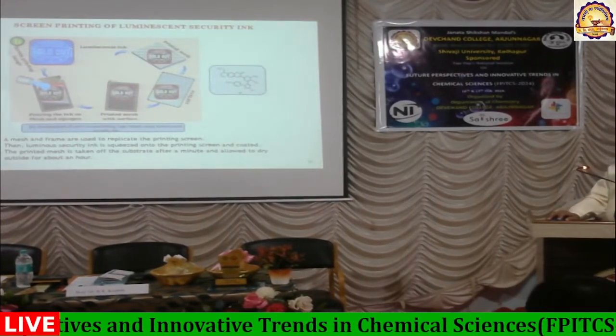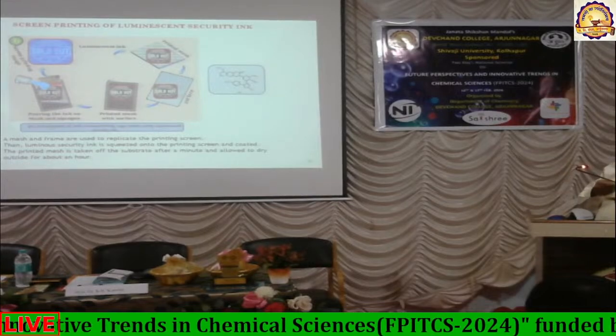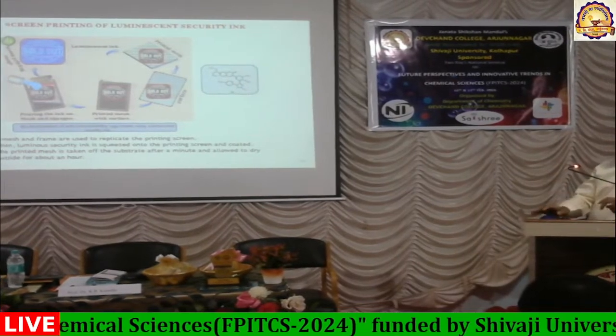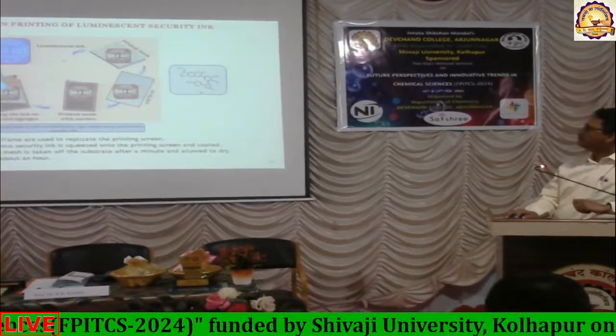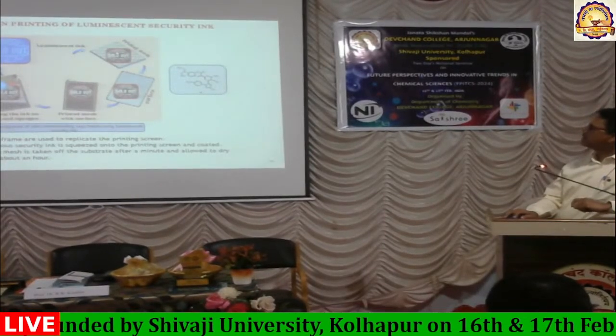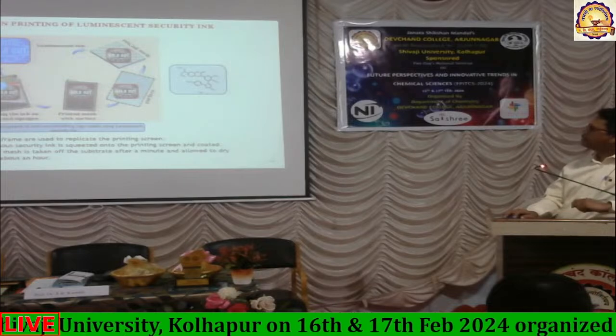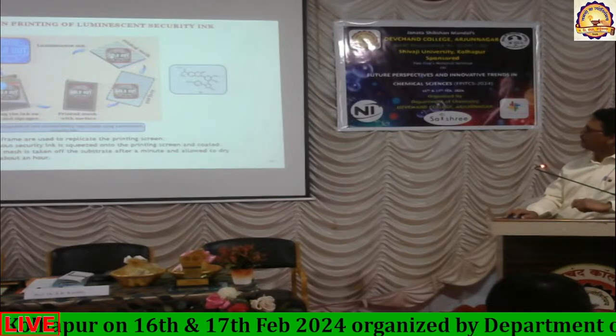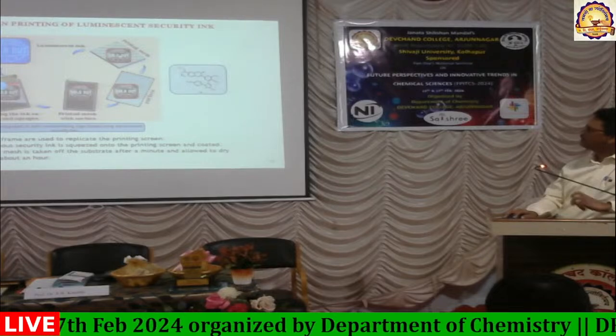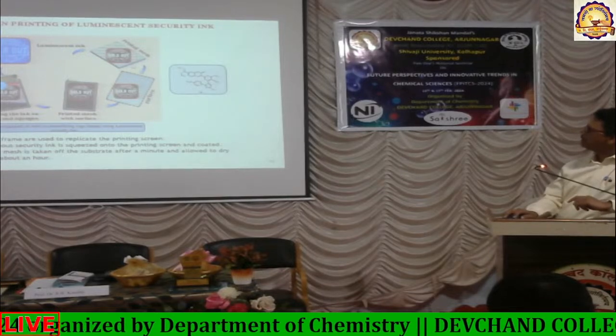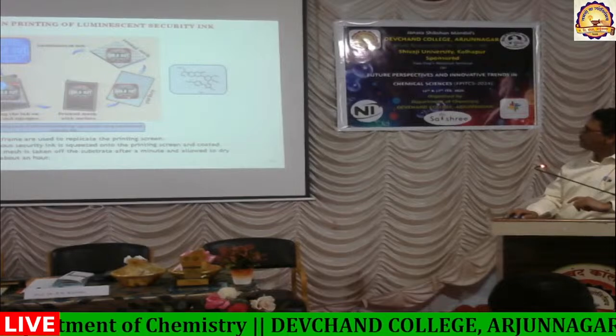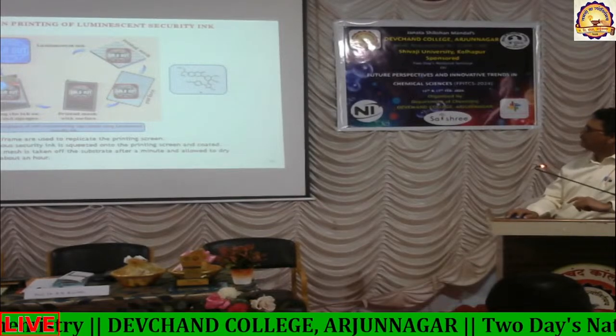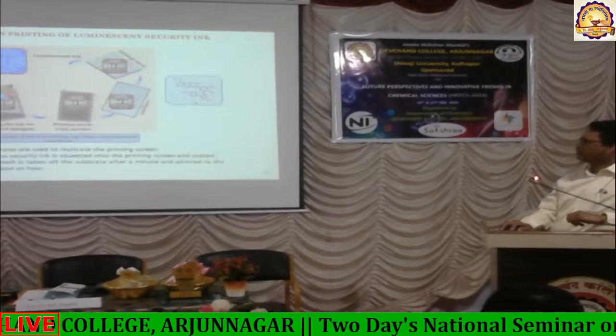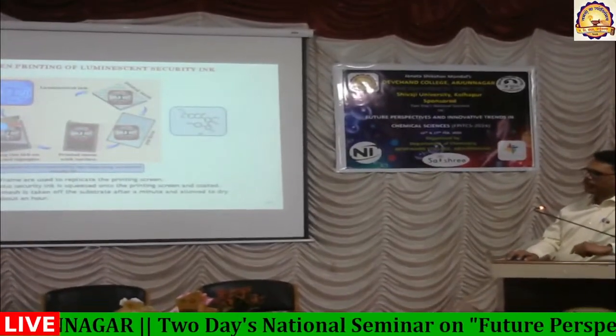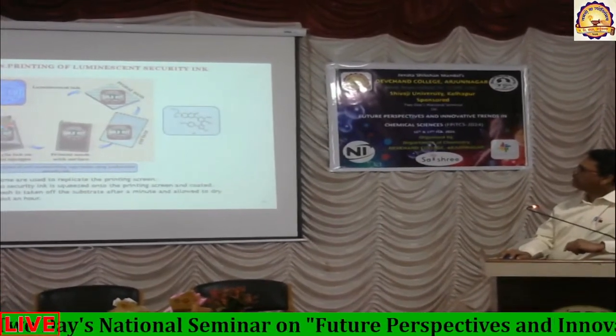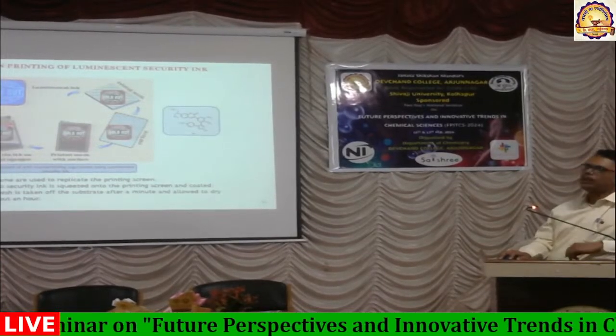We made a screen printing. That is because the hologram that we see on the product, the same kind of hologram can be synthesized where luminescent ink is taken on a printed mesh. This is the printed mesh with lots of holes here. With this same kind of structure, the mesh is taken and pasted on a surface, and this will be squeezed with the compound, that compound that we have prepared, as I explained to you, and then we get an impression of this, which can be seen only in the UV light.